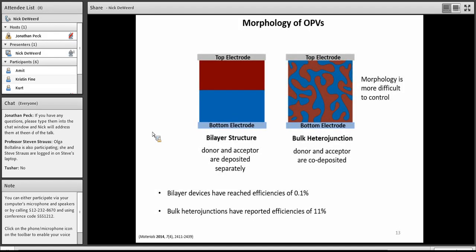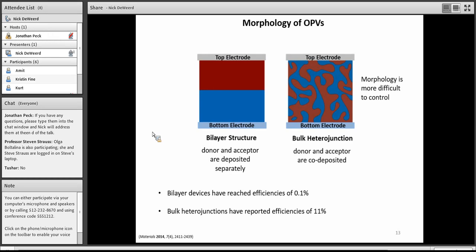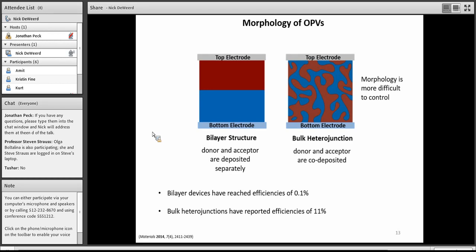Moving forward, I want to spend some time talking about morphology and the basic device structure that we use in OPVs. There's traditionally considered two different types of device structures. That's the bilayer or planar structure and the bulk heterojunction structure. The bilayer structure is relatively straightforward. It's just a donor and then an acceptor stacked on top or vice versa, depending on the type of architecture you're using. However, it's thought that the charge separation actually occurs at the amorphous interface between that donor and acceptor. You can imagine that the surface area of the donor-acceptor interface is going to be smaller in a planar structure or a bilayer structure.